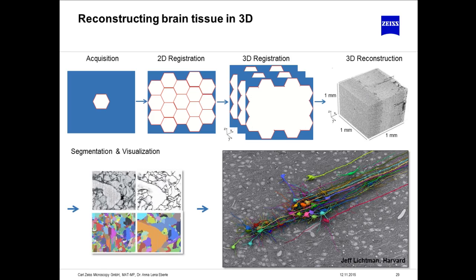The 2D images are stacked in the third dimension to reconstruct the volume that you previously sectioned. And the data set is then in the end also segmented, and the reconstructed components of the volume can then be rendered and visualized, as again shown on the right bottom of this slide. And this last part, the segmentation and the visualization, is maybe the most exciting one, because this is still subject to cutting-edge research, with groups all over the world working on different strategies and different approaches to solve this challenge, especially for larger amounts of data.